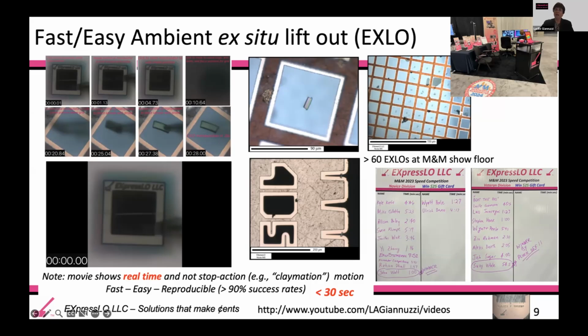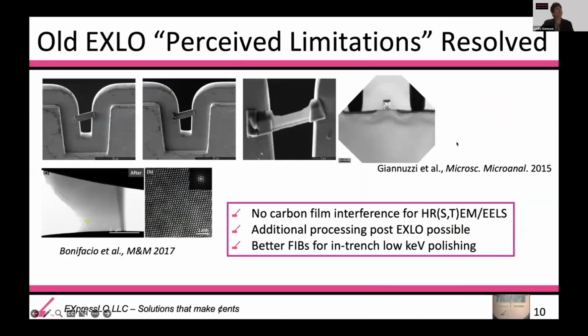At M&M 2024, we actually operated our system completely remotely. So we left our system in Florida, and we used complete remote operation and followed up with a contest that way. So the old perceived limitations of ex situ lift out were completely resolved. We don't have to worry about a carbon film. We can put samples on these patented slotted grids, and we can post thin them. We can even do argon ion milling, for example, and we can make very, very thin specimens for high resolution